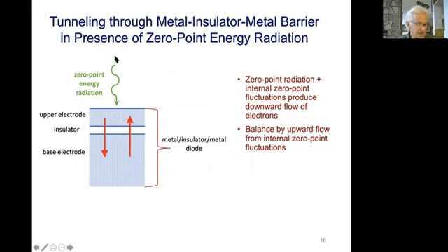And this upper electrode is very thin. It's so thin that if radiation, any sort of radiation, is absorbed, light is absorbed, it creates hot carriers. And these hot charge carriers of electrons can then travel through this thin upper metal electrode before they're absorbed, and then they can tunnel through or go over the barrier that's between the upper metal electrode and the lower metal electrode.